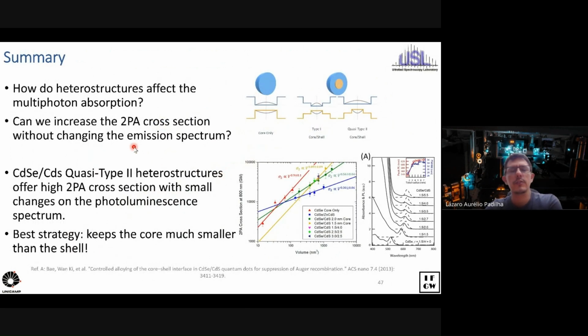So I want to finish this talk by telling you that, yes, it's possible to change the two-photon absorption cross-section in nanomaterials without changing the emission energy. And there's a lot of interesting physics still to study in this field. For example, we still have to learn if it's possible to really enhance the oscillator strengths in order to have pretty high two-photon absorption cross sections. And in this route, it's probably important to understand what causes the enhancement in nanoplatelet type of structures. So for the core shell structures, the best strategy you have learned is making a core much smaller than the shell, and you can have pretty good volume dependence.